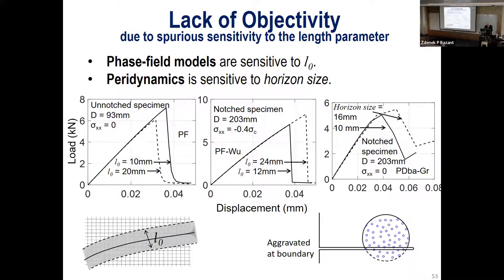So let me now discuss the last point I mentioned, objectivity. That's a basic requirement for any model. It must not depend on the human choice. If some parameters can be chosen arbitrarily and change the results, we cannot play with that to fit the data. So in phase field, it is the width of the band, and it has been shown in the literature that it has significant effect on the response. If you change it, you fit results better or worse.